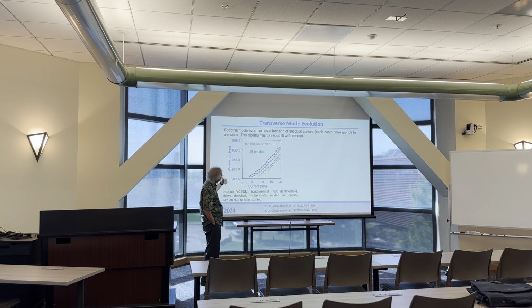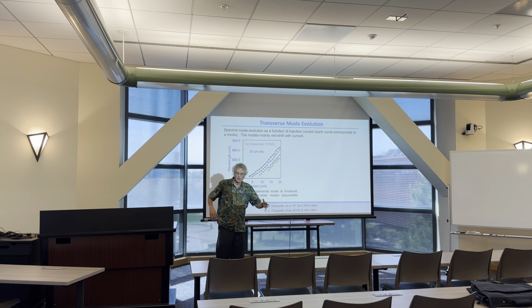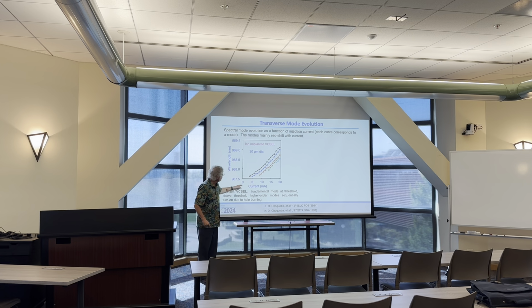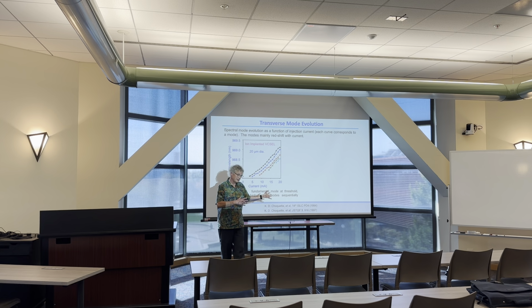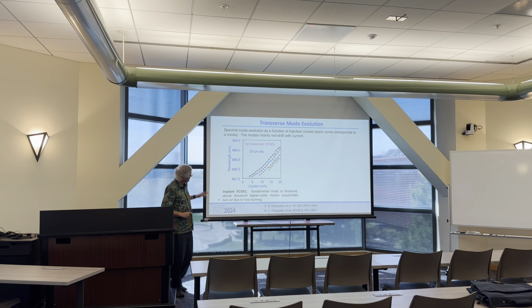Basically what this is tracking is the transverse modes of a microcavity laser, in this case an implanted device, as a function of current. Each of these lines corresponds to a different transverse mode. So the first one here, longest, will be the fundamental mode, and we climb up as we go. This is very much what we saw in this time frame, where you got the fundamental mode lasing at threshold, but very soon, because of hole burning, we would see other modes sequentially turning on. Of course, they're all shifting, because this is CW, so you're heating up the whole structure, and the index is increasing, and so the whole thing is basically shifting to the red.